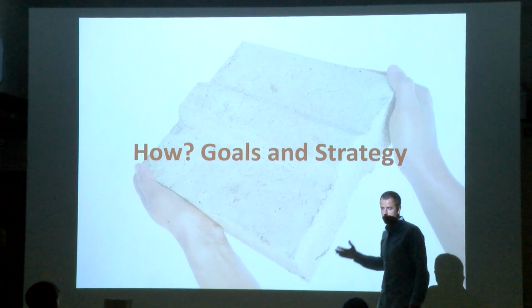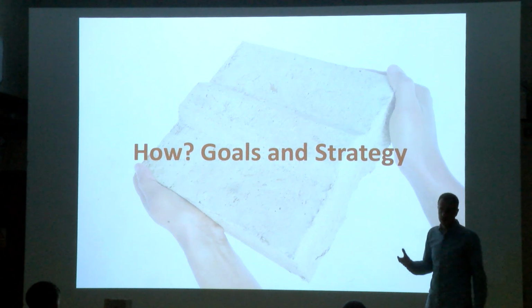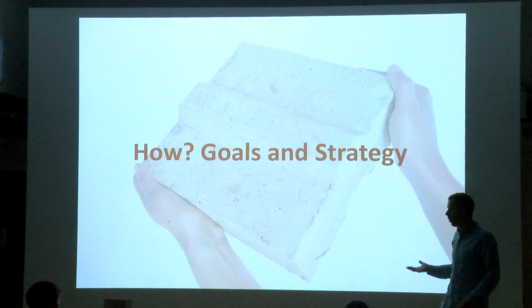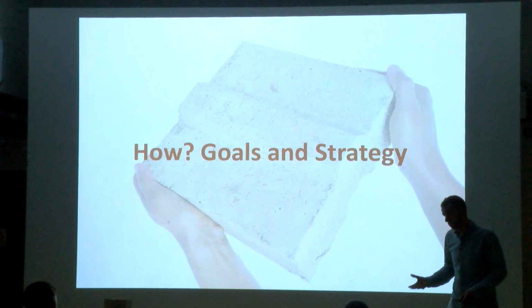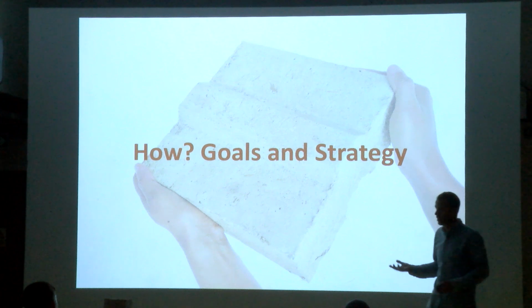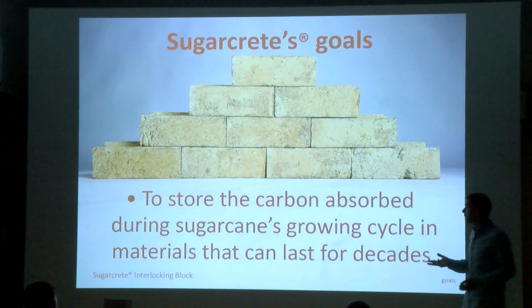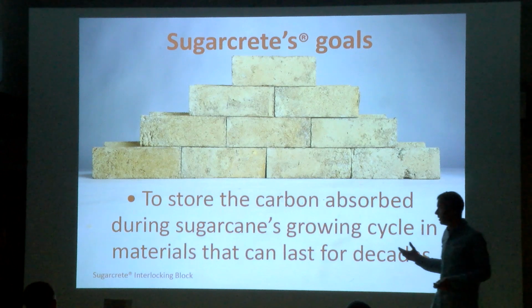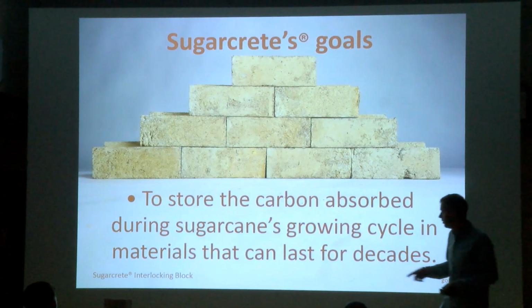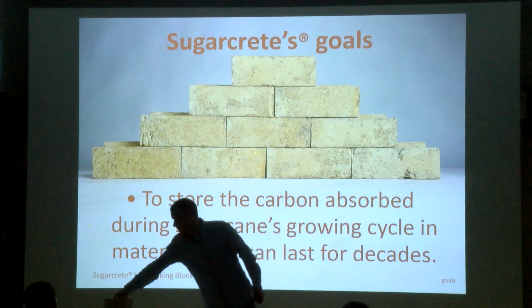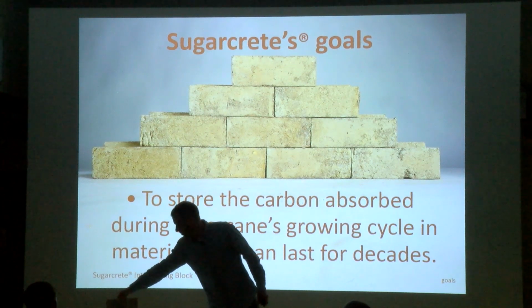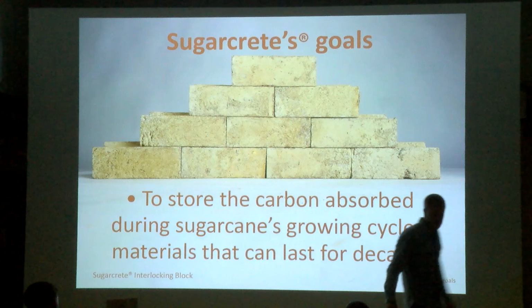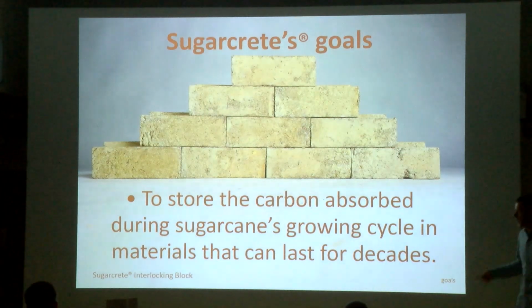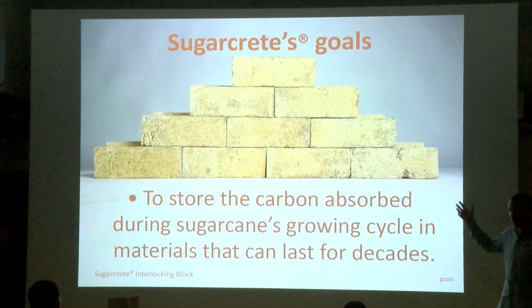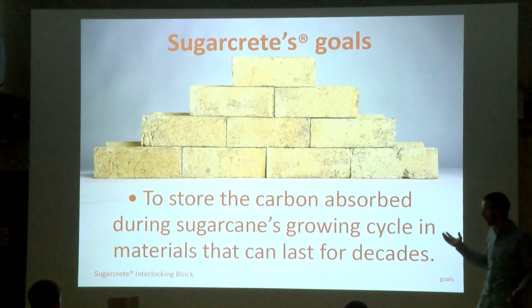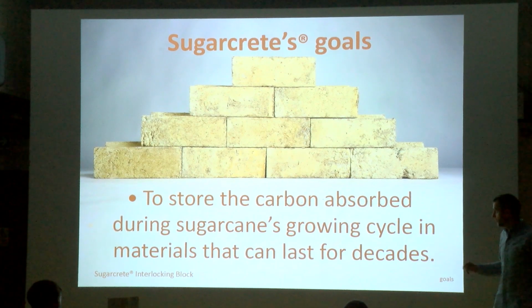So all that sounded very well, but we also wanted to set up goals and strategies that would allow us to work with the industries that are producing and harvesting sugarcane in an ethical way. The main strategy and the main goal that we set up was that we could use this material to store carbon. So this is one of the blocks that we are producing currently in India. You can pass it around if you want. And each one of these blocks, if they are produced locally, sequesters 1 kg of carbon each. That means that if this is implemented as a construction material in these areas, it could become a carbon sink, and it could become one of the largest carbon sinks in the region.